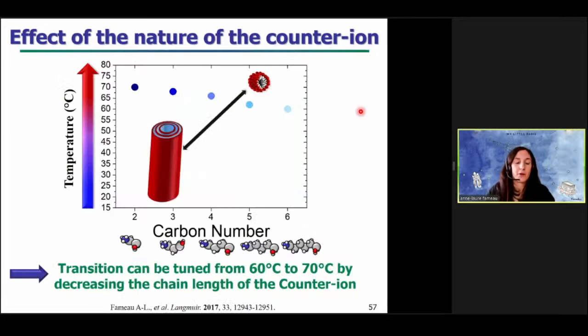Again, we determine the temperature transition between tubes and micelles as a function of the carbon number of the counterion. And as you can see here, by decreasing the chain length of the counterion, we increase slightly the temperature transition from 60 to 70 degrees. So when you change the nature of the counterion, you can slightly tune the temperature transition, but it's still too high for a lot of industrial applications.